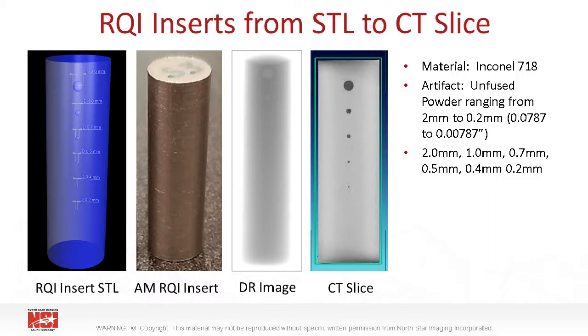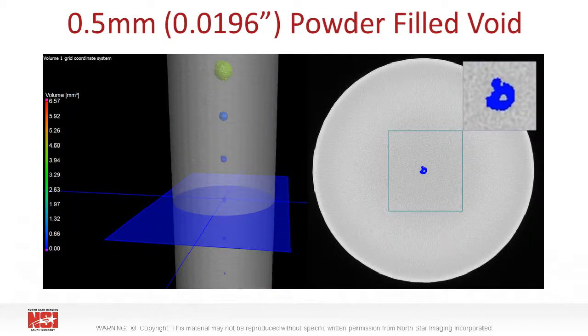Based on the non-spherical shape of some of the other indications and the undersized measurement of the 0.2 indication, it appears that the print resolution was likely not able to accurately print the 0.2 mm spherical void.